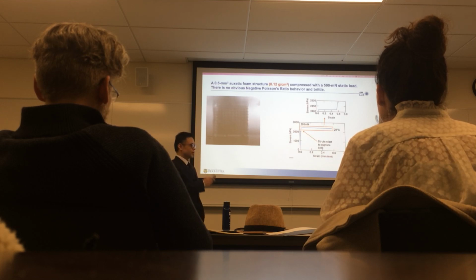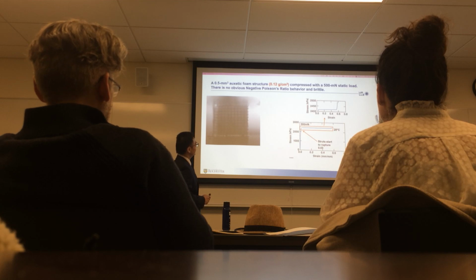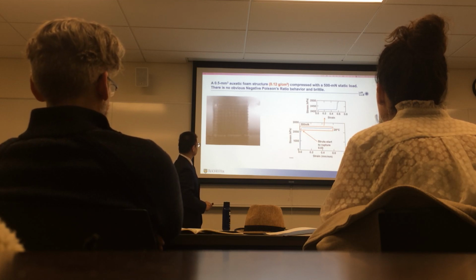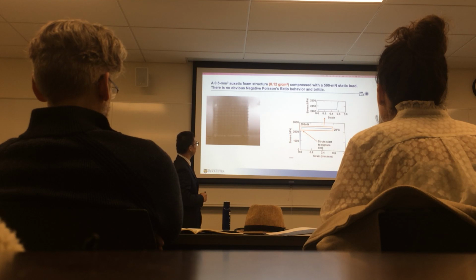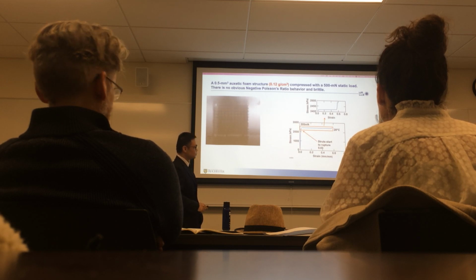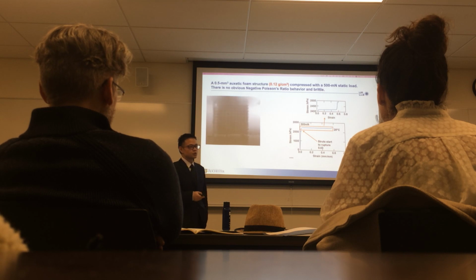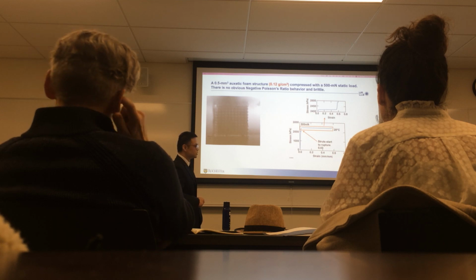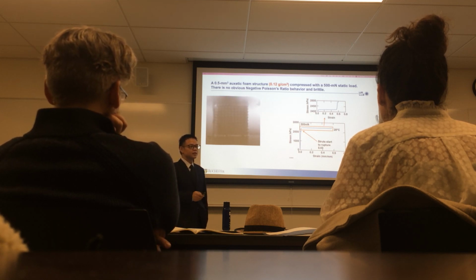This time we broke the foam with 500 millinewton force, but we still didn't see obvious negative Poisson ratio behavior. They still shrink in the vertical direction, and we found this structure is very brittle. It breaks at 3% strain. As I said, if you want the foam structure to absorb more energy, you want more strain in the plateau absorption area, and we also want this structure to be more elastic. So one easy way is to decrease the thickness of the unit cell.